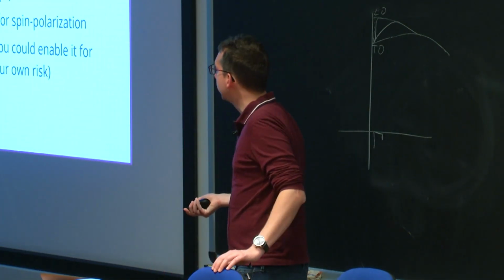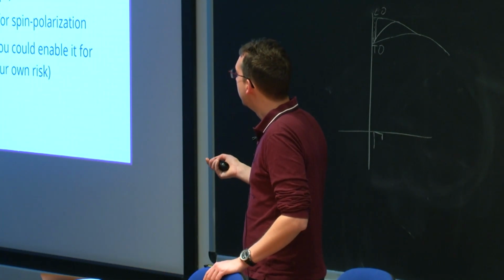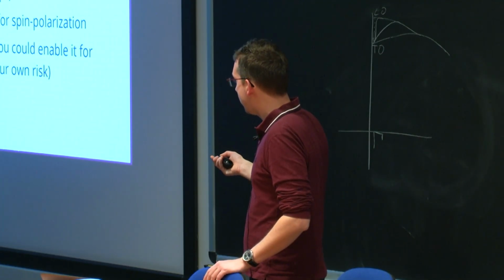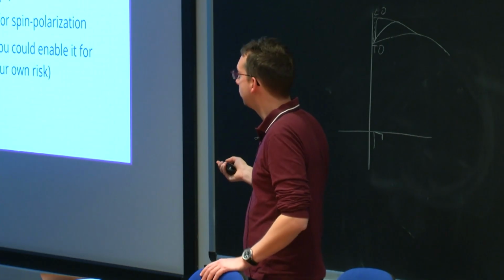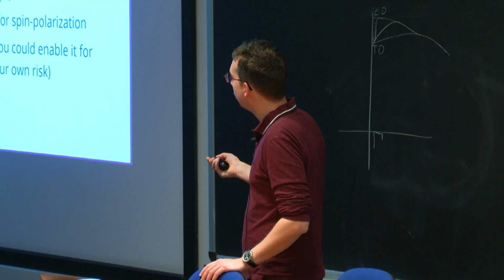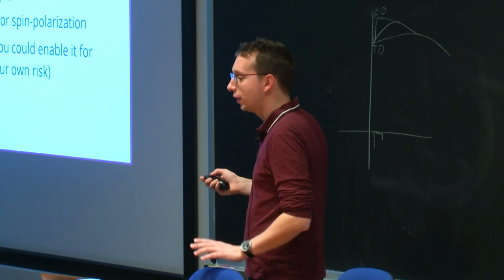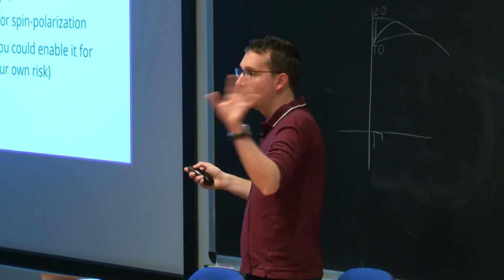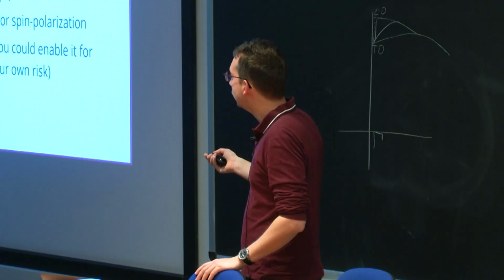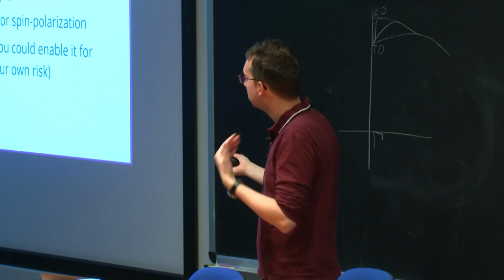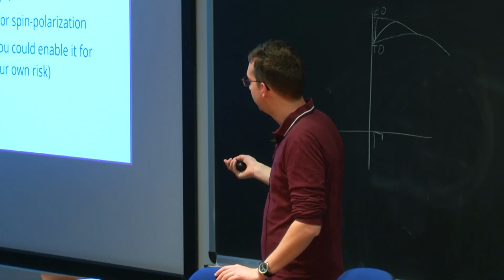The code has some important limitations. So in particular, only norm-conserving pseudopotentials, only local density approximation, so no GGA. I am sort of working on that, but it's not my priority. So if you really, really need the Raman tensor with PBE, you contact me, and maybe we can arrange to do it a bit faster. All the rest of the code was done like 10 years ago. This term I recently had to do for another case, so I said, why not put in Raman? Why not? Because we don't have time. But it is more or less there.